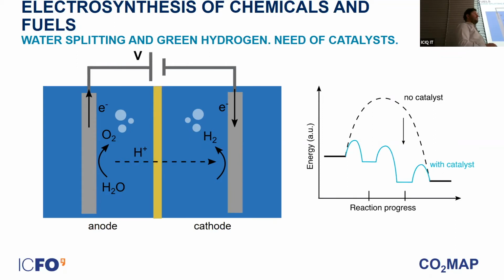In this kind of system, you need to design catalysts that reduce the energy required to drive these two reactions, so as to lower the energy input from the solar cell that you plug into these electrolyzers, if you wish to run them using solar. So in order to use less energy, you have to design catalysts that improve the rates and the overpotentials of these reactions.